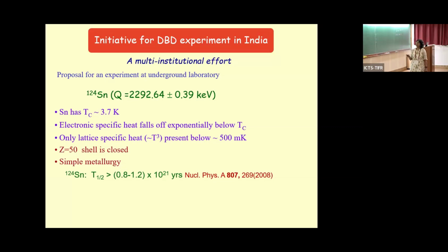From a nuclear physicist's point of view, tin has Z equal to 50, which is a closed shell, and metallurgy is simple. For tin, purification will be easier. What is known about tin is that the double beta decay half-life from the excited state decay measurements is about 10^21 years. Actually, even the normal double beta decay in tin is not yet observed.